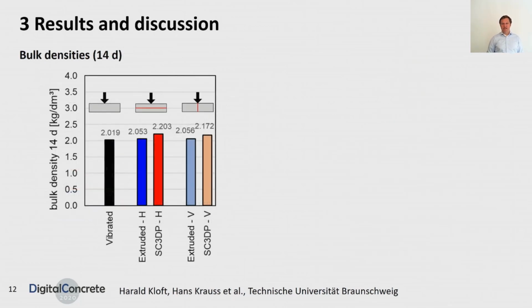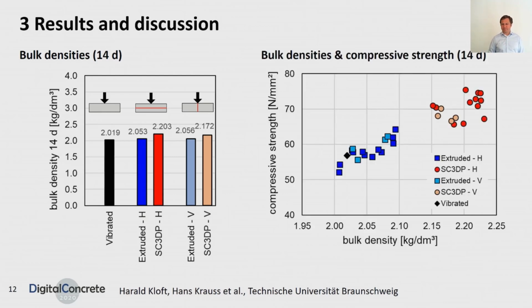And now I come to the results of bulk densities. We can see that as compared to the reference specimens here, we have slightly higher or significantly higher bulk densities in case of SC 3DP of about 2 and 9%. And on the right side, we can see that the compressive strength results do well correlate with the bulk density results, as is expected. And here we can also see that there is no significant effect of the main interface or the delay times on compressive strength. It seems to be dominated only by bulk density.